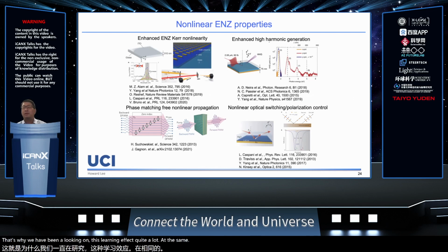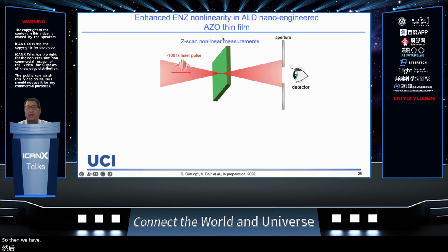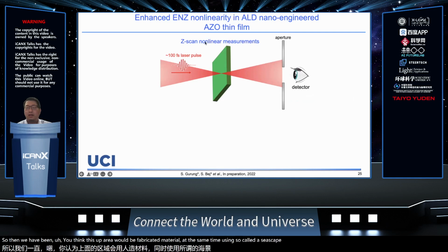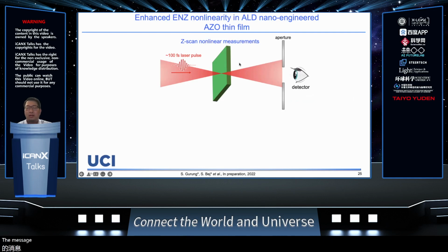At the same time, we want to see if we can use this layer engineering on this kind of ENZ material to enhance the nonlinearity in a really thin dimension, a really thin material. So we have been using this kind of ALD-fabricated material, and using the so-called Z-scan nonlinear measurement to measure the nonlinearity, which is a really simple measurement.